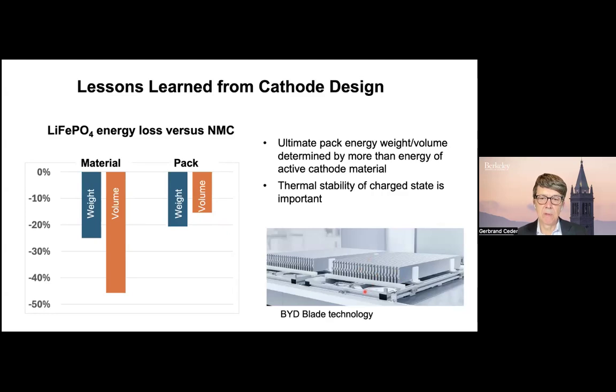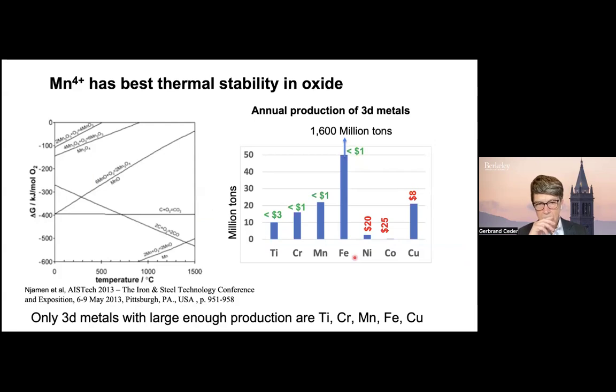And this is mostly because of the inventions done by BYD in so-called blade technology, where because the charge state of lithium iron phosphate has high thermal stability, you can actually make very large cells, and so the volumetric efficiency of the pack is much higher. The volumetric efficiency of an LFP pack, in the sense of if you take the volume taken up by cells versus the empty volume, is almost double that of NMC, and that's mostly because of the high thermal stability of LFP. So I think what we've learned from this is that yes, you should look at materials properties, but you also should think about other properties that affect the ultimate energy density that you will get in a pack.